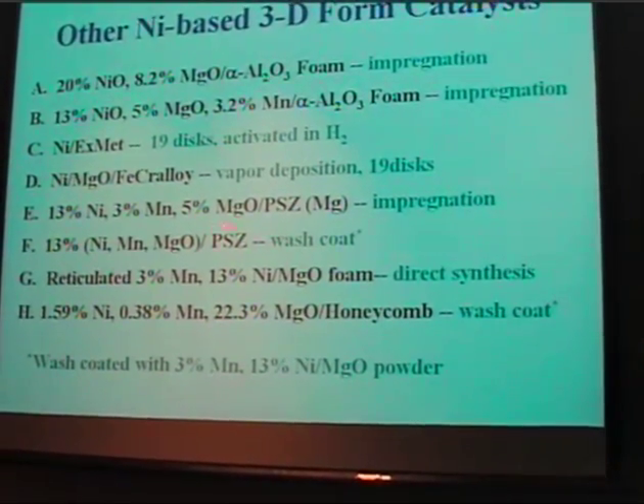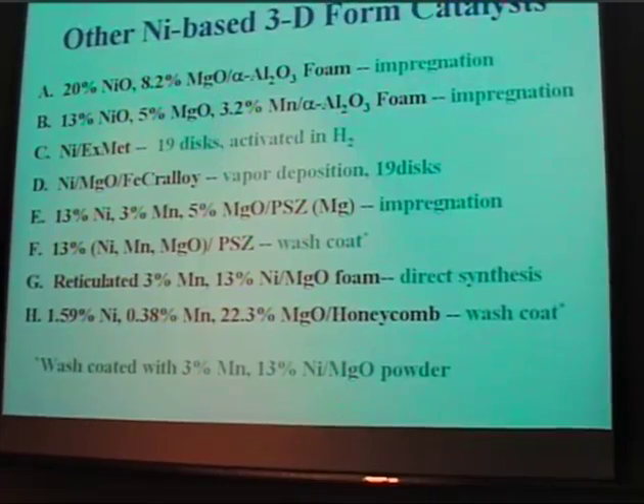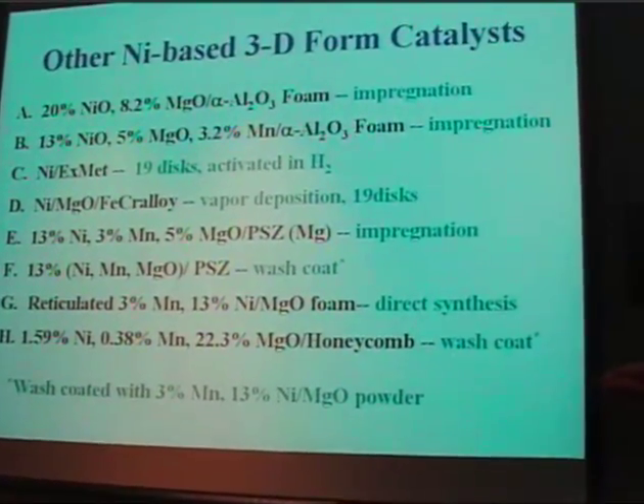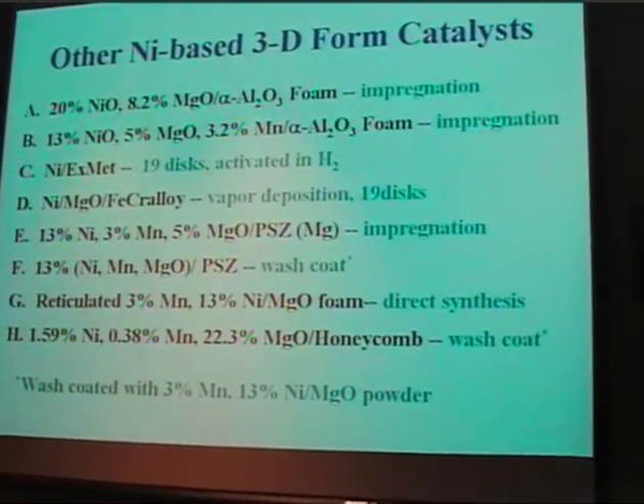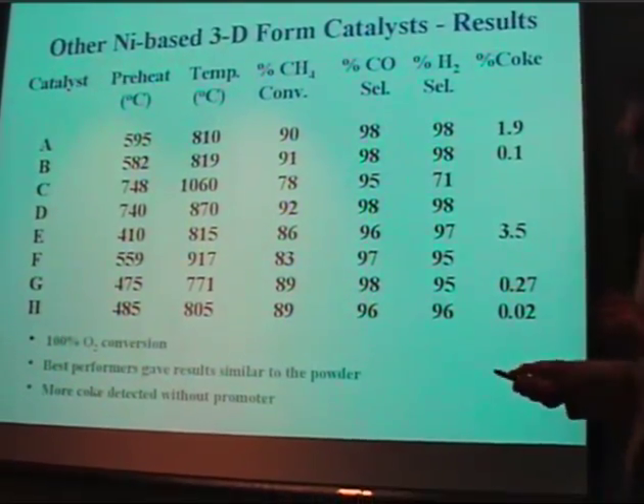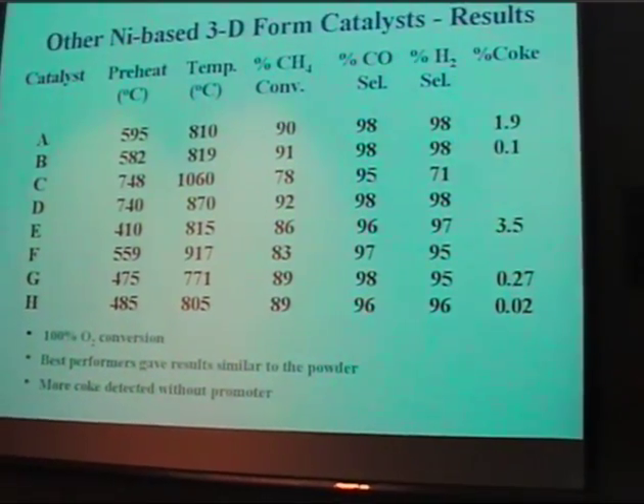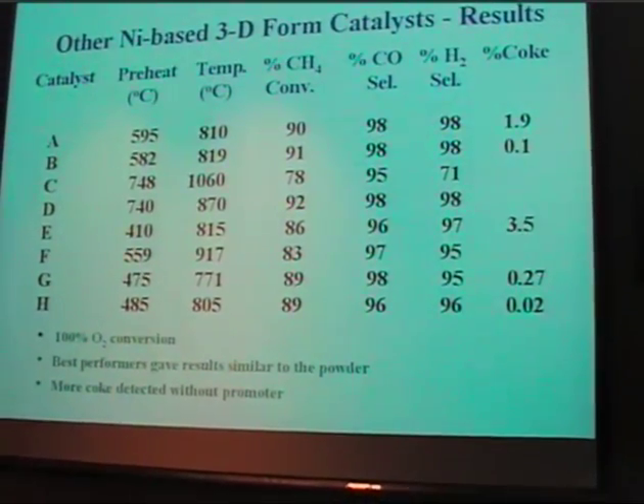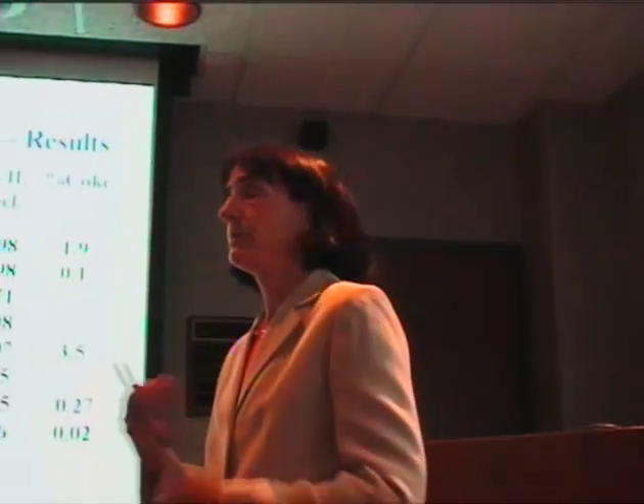Oh, this is the partially stabilized zirconia support, and we found that to be problematic actually. So that turned out to be not preferred in the case of nickel, unlike rhodium. But it looked good, and we were getting data that was fairly comparable to the powder, so we felt good about our powder screening program because that was good for higher throughput and finding new compositions for our reaction. It worked out well, and then we could take the preferred materials and move them into this type of a program.